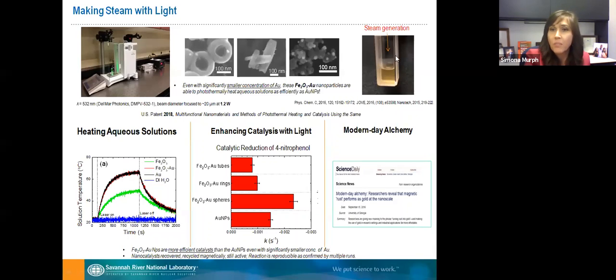And you can even see here some of the steam that was created at the top of these vials. Of course, we didn't see any boiling. That means everything was getting hot right there, in close proximity. If you take a look here, we replaced some of the gold with iron oxide, a cheaper material. You can see here that the gold iron oxide is heating as efficiently as the gold nanoparticles. In 20 minutes, we can reach around 70 degrees Celsius with the gold iron oxide nanoparticle. This was quite exciting because suddenly we were able to say, hey, we have a slightly cheaper and very abundant material, iron oxide, and actually we can get the same heating effect.